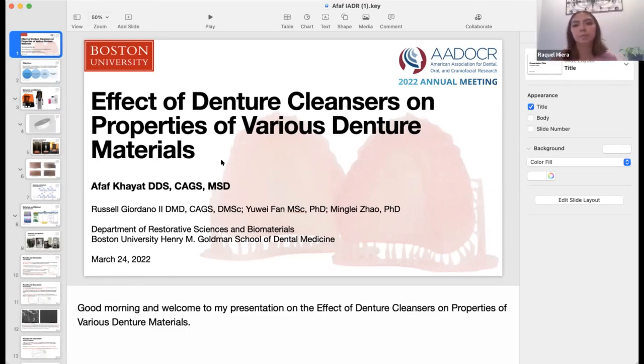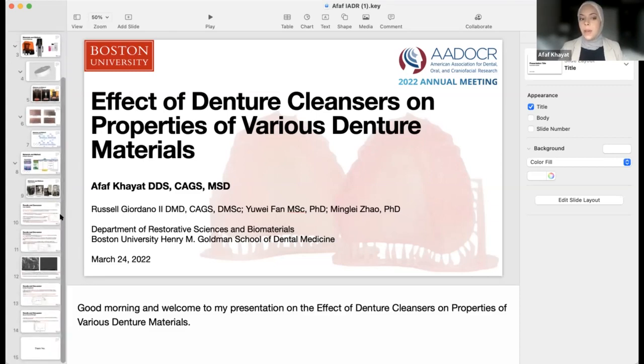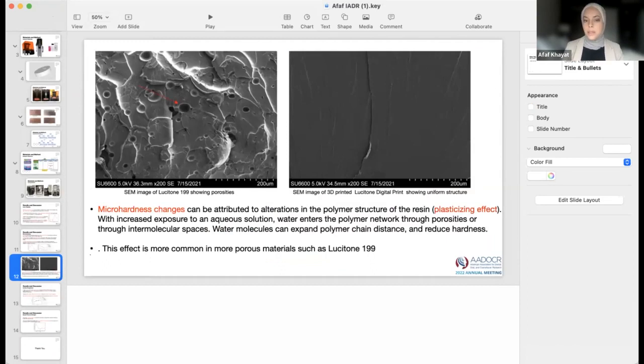Yeah, so for the Lucitone 199, which is the heat polymerized resin, I did expect that, only because of the way that it's processed. Now with 3D printed resins, the structure is a lot more uniform. I did have a slide here after an SEM analysis, which does show how the Lucitone 199 has more porosity. So that definitely can affect the color stability of the resin. And also the way that it's made, with the monomer and everything, I think that could also have an effect on the stability of the color over time.